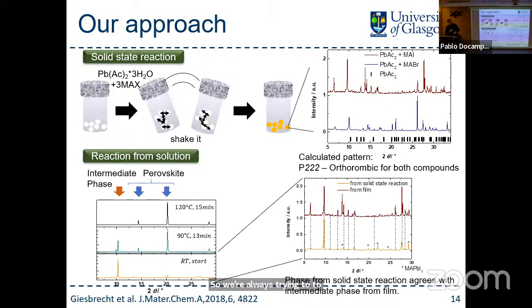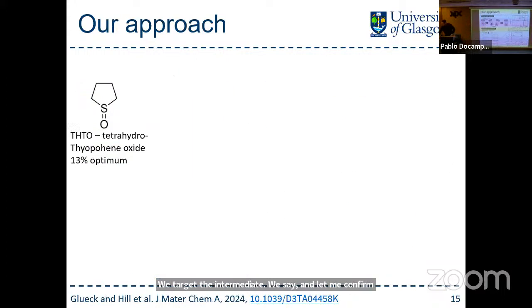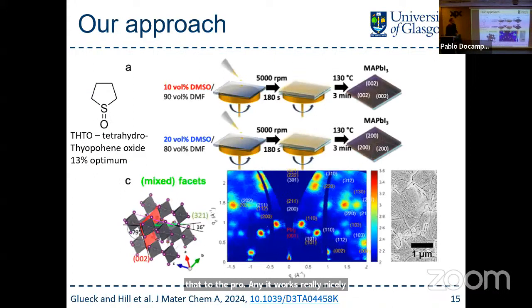I'm not going to bore you with the exact details here. There are many ways of crystallizing the materials. I'm breezing through this quite quickly, but the important message here is not the specific route. It's that we can make very large crystals that are all oriented in the same direction. We target an intermediate phase, which crystallizes out, and then we convert that to the perovskite phase. And it works really nicely. We basically use solvent additives to achieve that, and it gets incorporated into the structure. It directs the growth, and then we convert that to the perovskite structure.